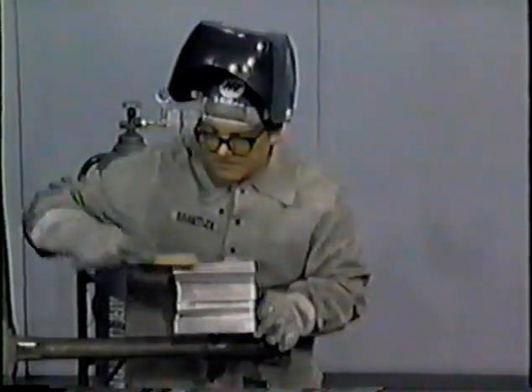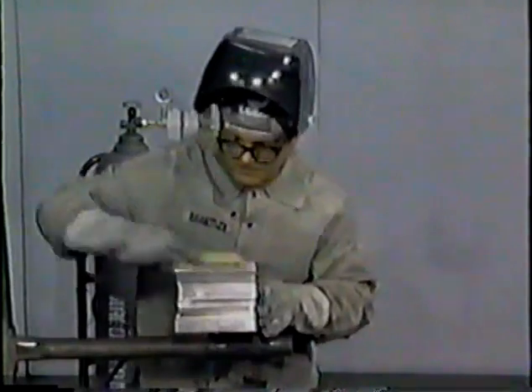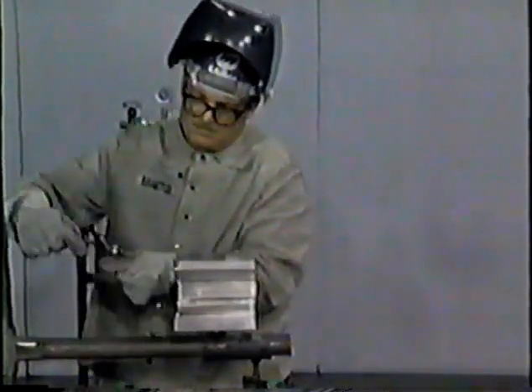Now run the final weave bead, or cap bead, as shown here. Turn off the welding machine, wire brush the weld, and quench the workpiece. Now have your work evaluated. The final weave must be no less than 3/4 of an inch and no more than 1 inch wide.